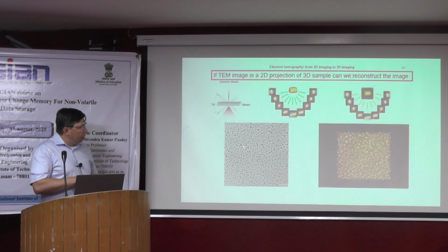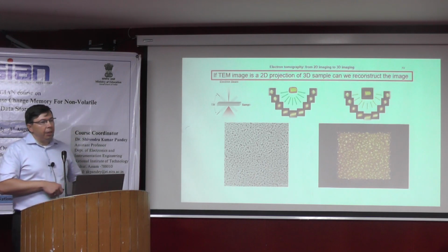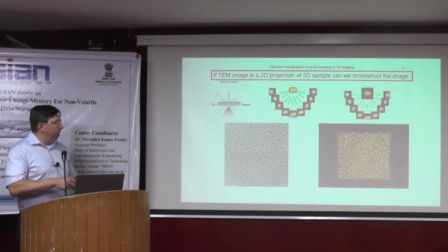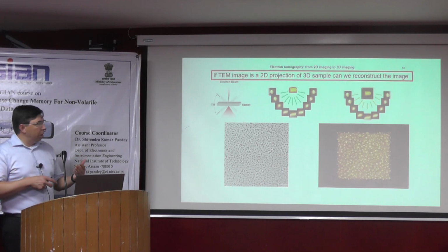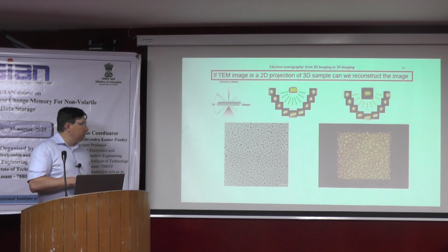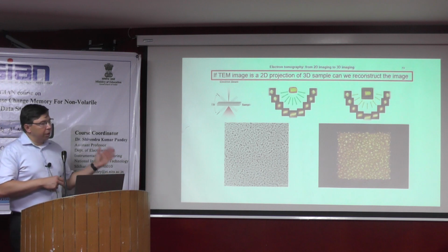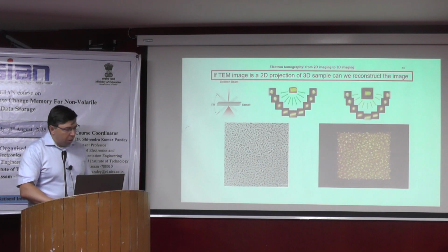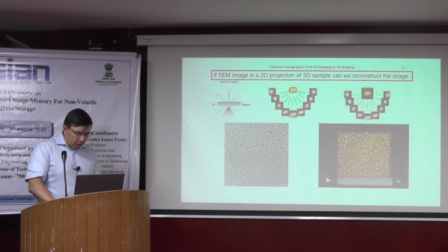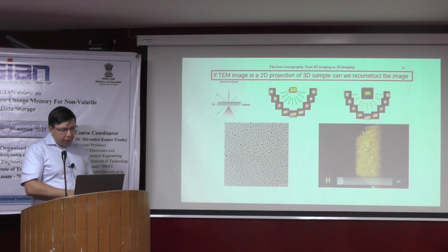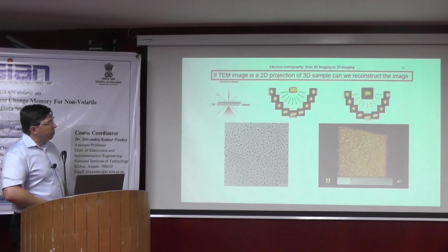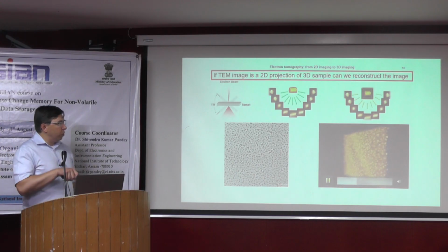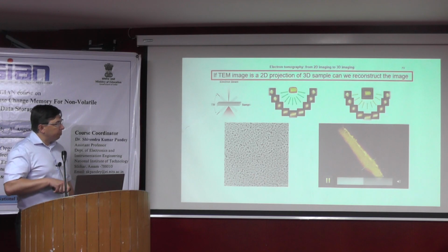You see here large fraction and small fraction, and the interest here is how they are distributed in the sample. Maybe the larger fraction can go to the surface, or it can stay in the bulk, or it can be a mixture of this. So after the 3D reconstruction, like here, you can nicely see that a large fraction is sitting on the surface of your specimen.